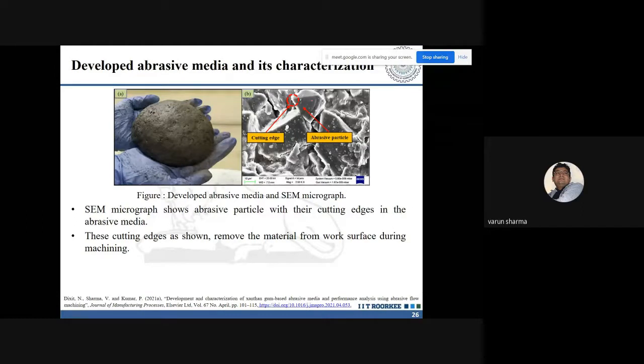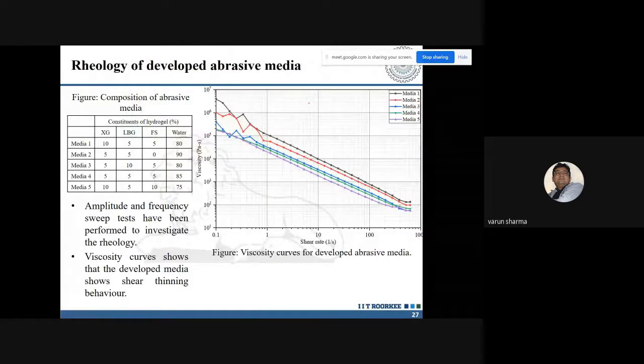Now the abrasive particles were embedded, and through SEM we characterized it and found that we were able to produce a highly dense structure, and this was what we used for the abrasive medium. Now, before using it for actual material removal, because if I have to get a micron or nano level of surface finish, my abrasive media should be stable at temperature for a longer duration of time. We characterized this media because only then could we attain a micron or nano level of surface finish for the 3D printed object.